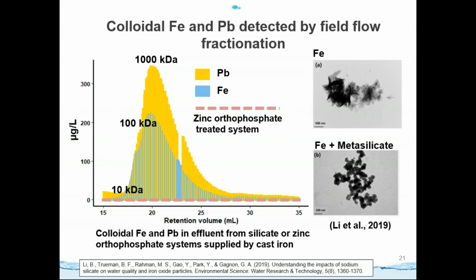As we can see in the figure on the left, the red dashed line is the signal of the lead or iron from the zinc orthophosphate treated system. We can see there is no signal of colloidal iron or lead. But in the presence of sodium silicate, we can see two significant peaks of colloidal iron and lead. The blue peak is the colloidal iron, and the orange peak is the colloidal lead. The size is from 10 kilodaltons to 1 million daltons. So it is obvious that we did observe a high concentration of colloidal iron and lead at the high dosage of sodium silicate.